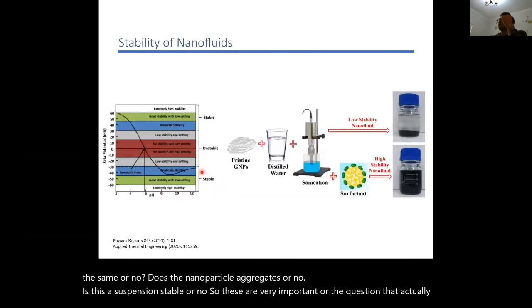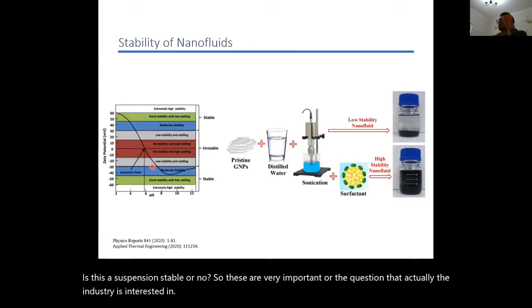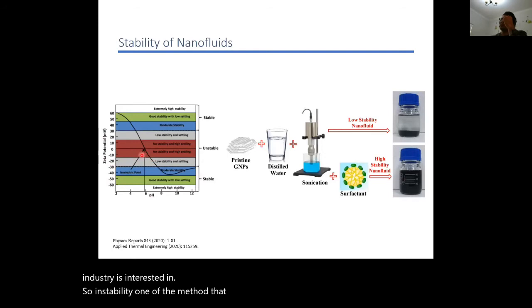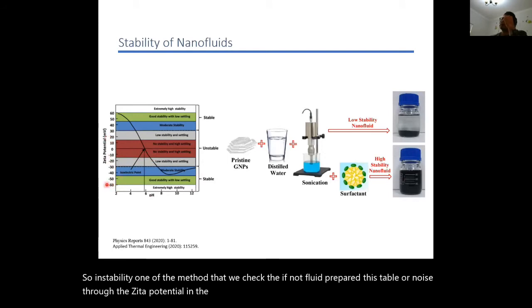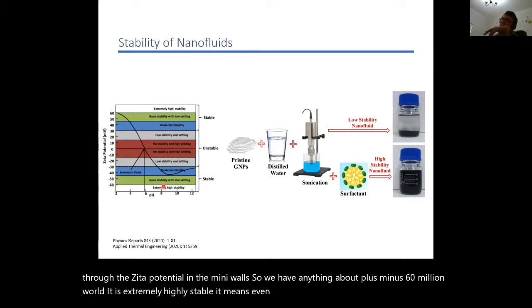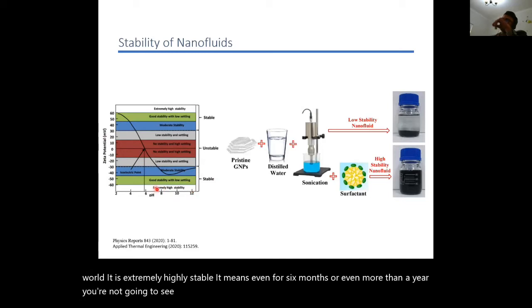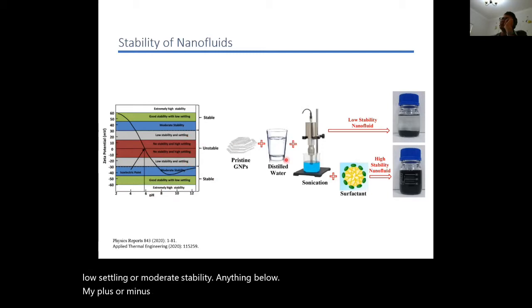In stability, one of the methods we use to check if a prepared nanofluid is stable or not is the zeta potential in millivolts. If we have anything above plus or minus 60 millivolts, it is extremely highly stable. It means even for 6 months or more than a year, you're not going to see any aggregates or sedimentation. However, if you're in the range of plus or minus 40 to plus or minus 60, you are within the range of good stability with low settling, or moderate stability. Anything below plus or minus 30 means that with time you're going to have sedimentation.